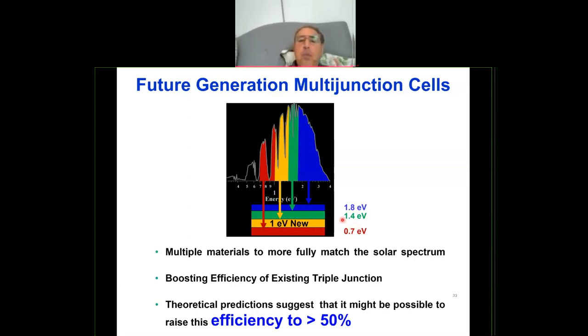Okay, so it's not easy to stack one material over another, because you need at least that they should match. And one of the major parameters, which is very important, is the lattice constant. So all these materials we're going to stack one on top of the other should have a similar lattice constant. But if one is bigger than the other, then you're going to have a lot of strain, and then you're going to have a lot of problems.